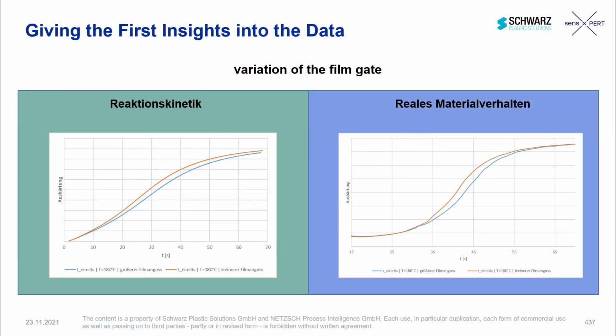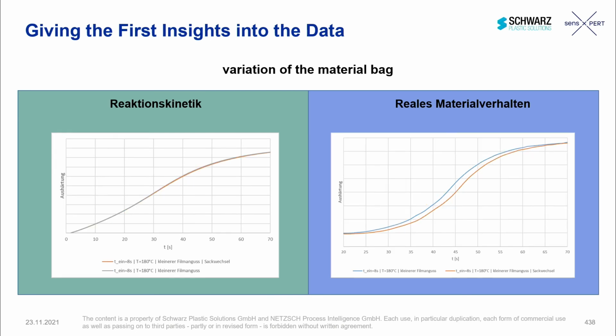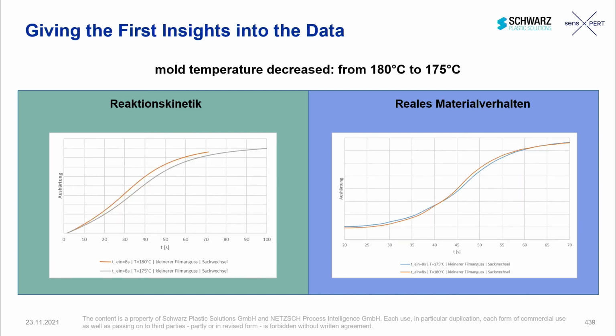On the other side, when varying the film gate, here we also have a different behavior of shearing and temperature influence. And also here we can see, in this case, reaction kinetics and real material behavior fit quite good together. But when we change the material bag, on the left side you can see pure reaction kinetics just based on the temperature measurement within the material that cannot see the back-to-back deviation. But we can see it during the manufacturing on the right side. So here we really have the chance to make a change within the process environment and to teach our artificial intelligence how to react on that and how to readapt the process.